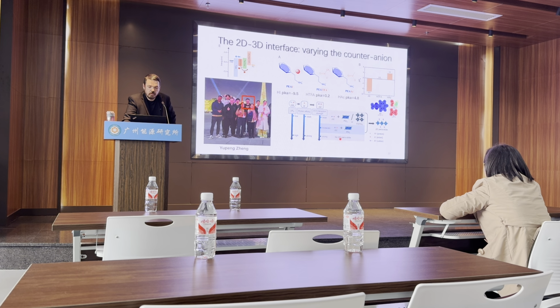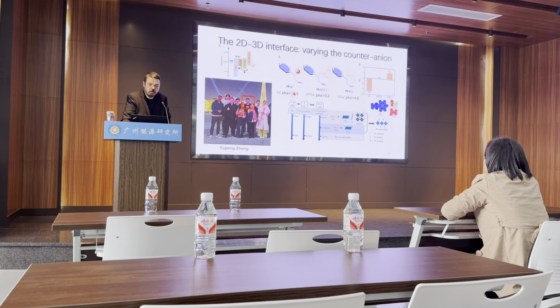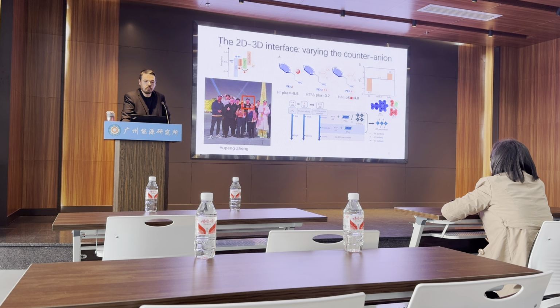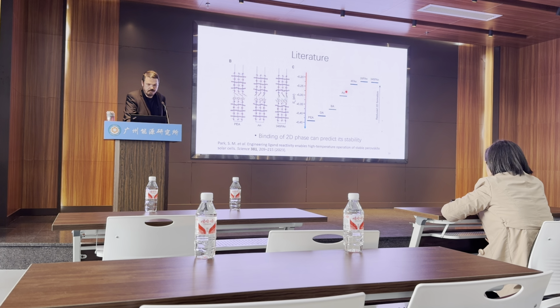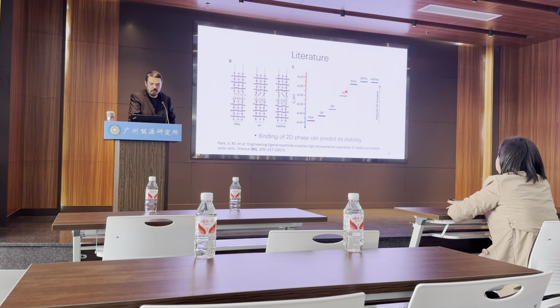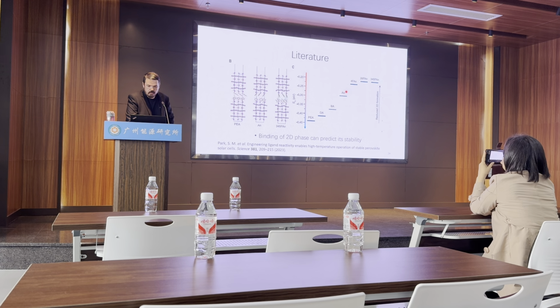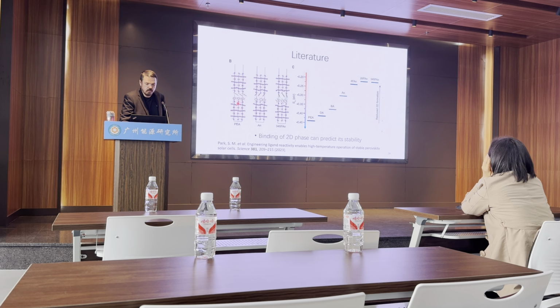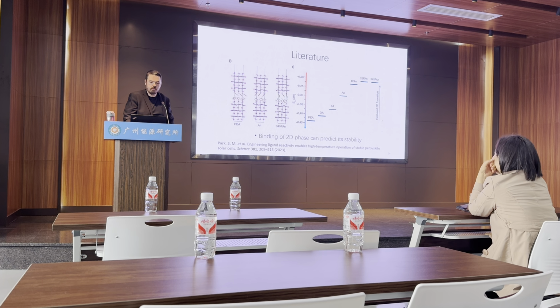And in this case, we don't get 2D perovskite. So when we use this passivator, no more 2D. This one, of course, is well-known 2D. So as our acidity goes down, our 2D phase also disappears. That's the result, and that's the result we needed to simulate. The literature is already quite good on this in terms of studying the 2D stuff. It's already known that the binding of the 2D phase, the binding of basically this piece to this piece, is what we mean by the binding energy.